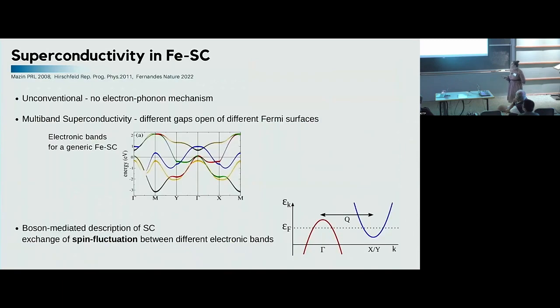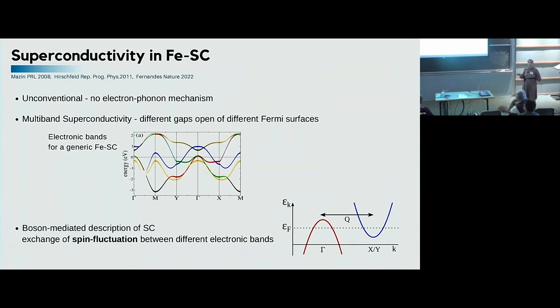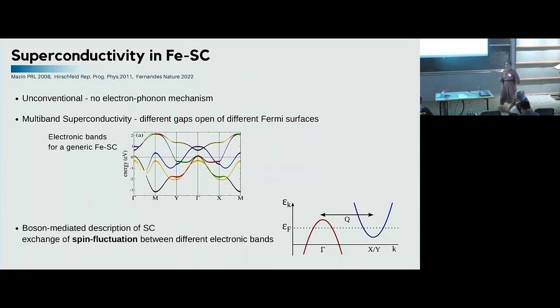Superconductivity in iron-based superconductors is unconventional, and in the majority of systems it is well proven that it cannot be explained with an electron-phonon mechanism. It is multi-band: you have several orbitals close to the Fermi level that form different bands, and superconductivity is realized by opening gaps on different bands. A weak coupling theory based on the exchange of spin fluctuations between nested bands at the Fermi level — in particular hole bands at gamma and electron bands — provides a good description of the superconducting phase and its phenomenology.